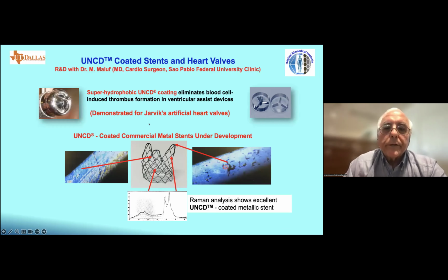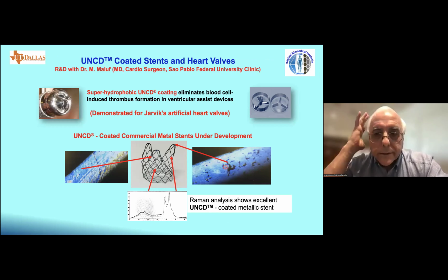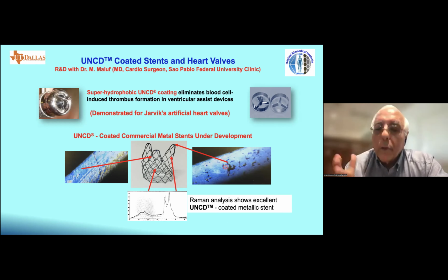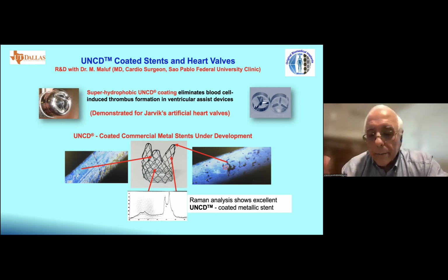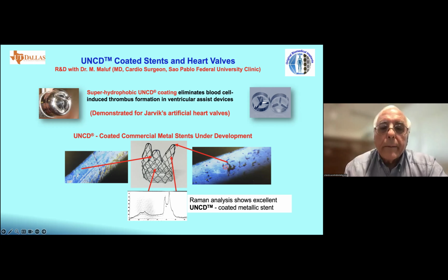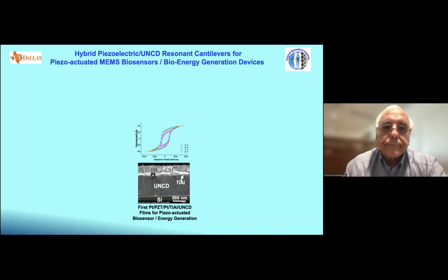So Robert Jarvik came to us to see if we could coat the valves of the artificial heart with UNCD to avoid the sticking of the blood cells on the hydrophilic surface. We have demonstrated that. We have a problem with FDA approval. And now I am collaborating with a cardiosurgeon in Brazil and demonstrated that the UNCD coating of the stent could be the solution to the many problems they have with the metal stents, cobalt, nickel, and chromium alloys.